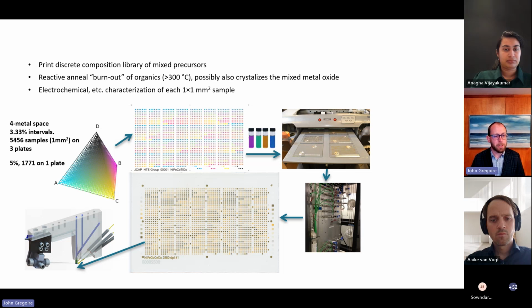So the question, it's interesting, it's almost the same number. There's a little over 5,000 samples in this space. This is with 4 components, but instead of 1 atomic percent, it's 3 1/3 atomic percent intervals, right? So this is how we started searching high order composition spaces by taking 4 different elements from the periodic table, making their metal precursor inks, and printing them at all possible combinations at 3 1/3 atomic percent intervals.